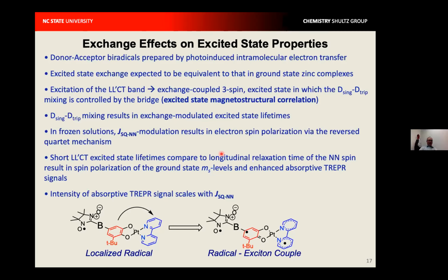So this is a great idea, and if the exchange coupling were due solely to the organic fragments and the platinum plays no role, which we know it does, by the way, then there wouldn't be much anisotropy to the exchange. But we think the platinum does play a role. We have a paper that just came out in JACS that shows that the spin polarization is dramatically reduced when you go to palladium. And so what we would like to do is more low temperature spectroscopic studies and to probe more closely the exchange and the zero field splitting in particular of the platinum biradical complexes. And we're working on that right now, but thank you for that comment. It's spot on.